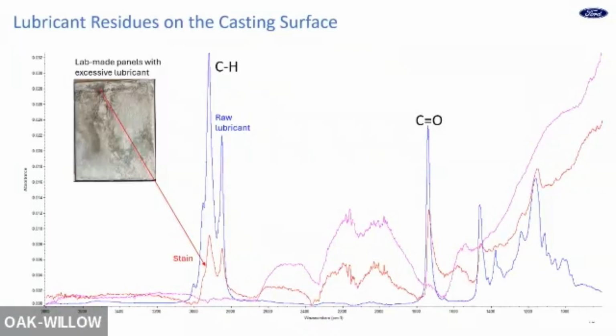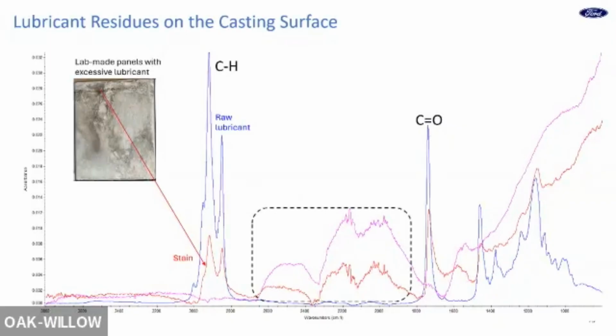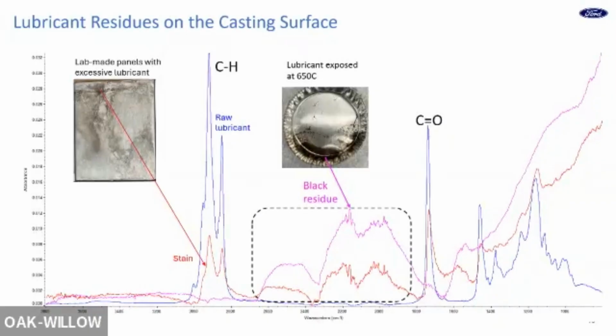So the blue line here is the FTIR spectrum of the raw lubricant. You can see the hydrocarbon or this kind of functional group. And we also collected a spectrum on the black stain area on the lab-made sample. You also see a similar hydrocarbon peak, but there are 3 bumps here that are not observed on the raw lubricant, the blue line here. To confirm what these small bumps are, we burned some lubricant in the lab just to simulate the casting process, and then we collected the spectrum on the lubricant sludge, and you do see a similar 3 bumps over here. So on the surface, you may have some partially oxidized lubricant, more like the original lubricant, but you also have some oxidized lubricant, like the sludge on the surface. Then how can they be removed in the alkaline cleaning process?